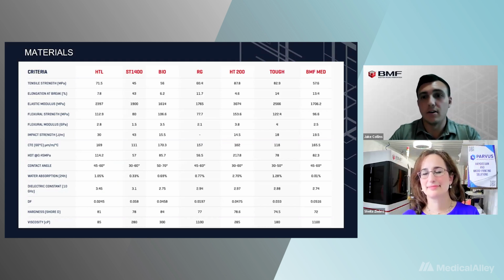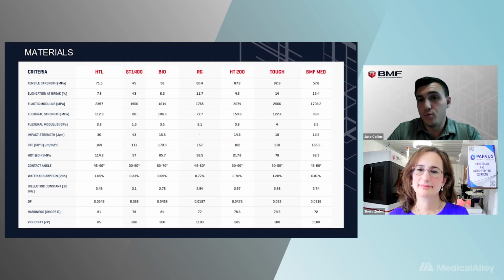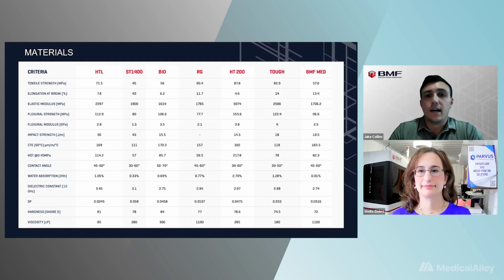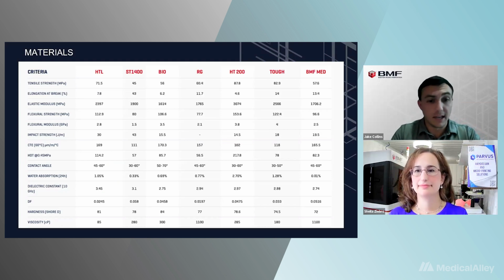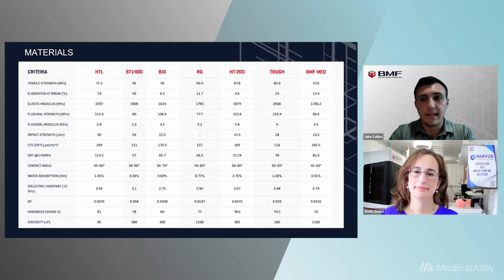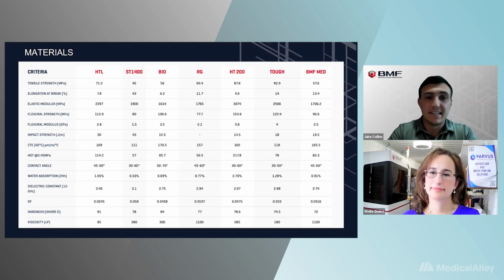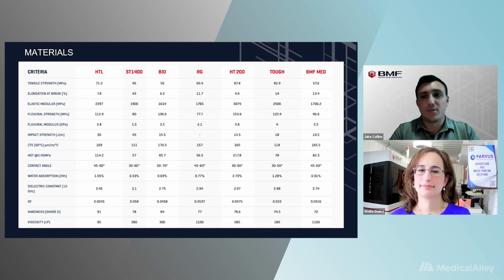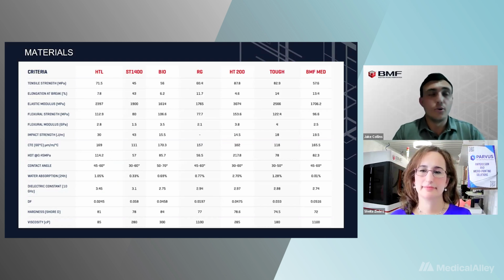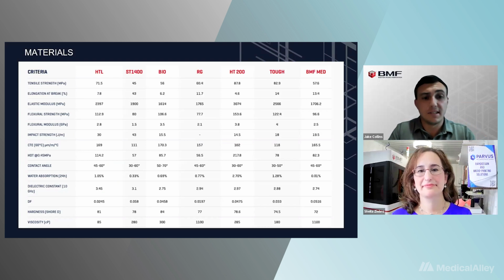Typically, the biggest difference here with a lot of our materials is that they are tuned for thinner layer heights and higher resolution, so they have more light blocker in them. We typically operate on our 10 micron system anywhere between 10 and 40 micron layer heights. Most typical DLP printers that are more hobbyist level or just larger macro scale parts are 50 micron and above for layer heights. So this allows us to get to a way smaller feature size in the Z and control that Z resolution a lot tighter. And part of that is due to the materials.